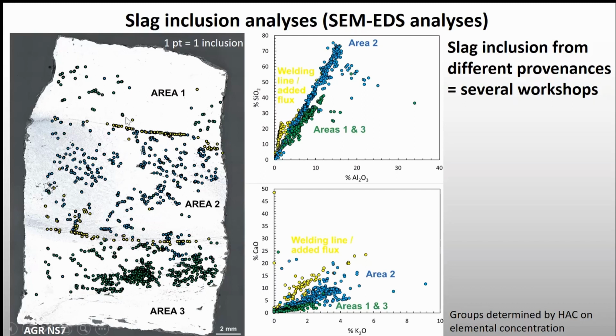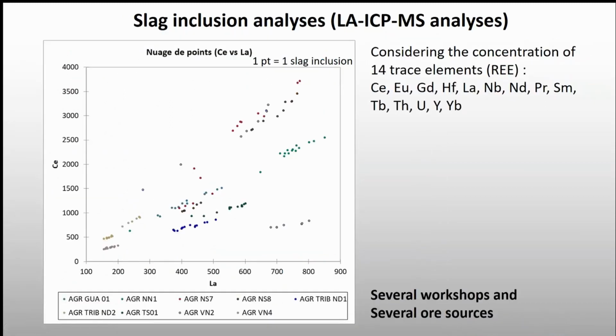And then also it shows that you see here the second area, the middle one, slag inclusions are blue, and they have a different composition, different ratios than the top and the bottom one, which are here in green. So this means that here we have, in fact, a cleft weld. We have inserted the second bar here in the middle inside a first one, which was open in two in order to make the weld. So the bottom and the top material are actually the same one. So there's not three, but two different compositions only.